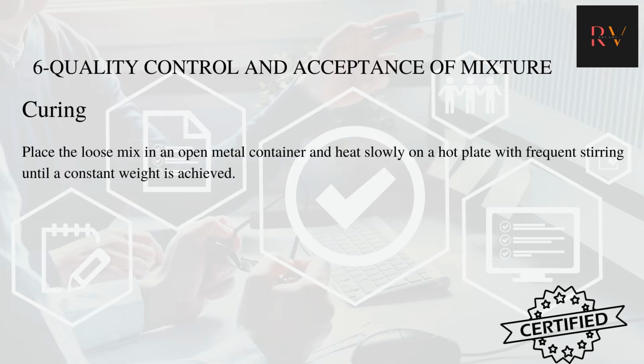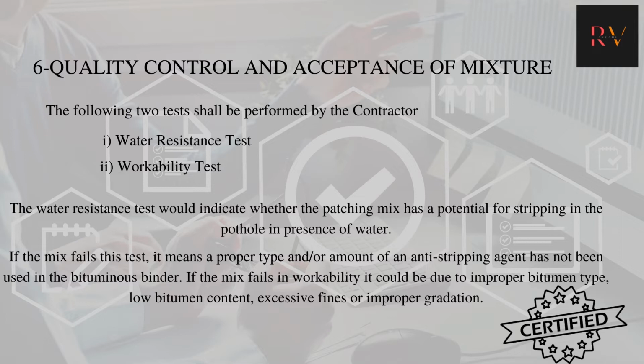So the following two tests shall be performed by the contractor, which are the water resistant test and the workability test. The water resistant test would indicate whether the patching mix has a potential for stripping in the potholes in the presence of water. If the mix fails this test, it means a proper type or amount of an anti-stripping agent has not been used in the bituminous binder. If the mix fails in the workability, it could be due to improper bitumen type, low bitumen content, or excessive fines or improper gradation. So I was talking about appendix 1.